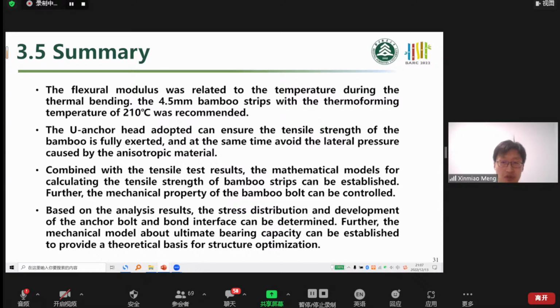And here are some conclusions for the self-anchor bolts. First, we found the temperature is related to the elastic modulus, and we need to optimize the temperature for each thickness. And the U-shaped anchor could improve the load carrying capacity of the anchor bolt. And we also studied the theoretical analysis based on elasticity and the thick shell or thin shell model. And we think that if we want to fully develop the tensile strength of the FRP and bamboo materials, we need to design its slope angle, its thickness, and also the inner diameter of the bolt.